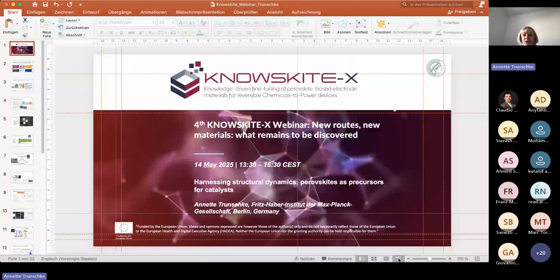But both of the materials are phase pure according to XRD. But if you have a closer look with electron microscopy, you see that these materials have surface defects. So you find very different surface terminations. In some cases, you find manganese enrichment here or here, but you find also samarium or lanthanum enriched at certain positions. So you have a very irregular surface termination despite the phase purity of the material.